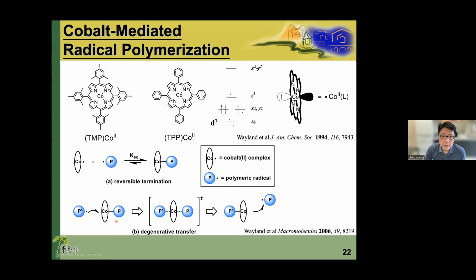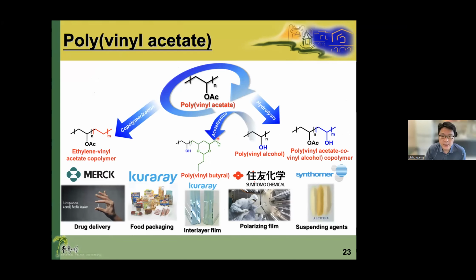And the feature of cobalt-mediated radical polymerization is the remarkable capability to control vinyl acetate. If you remember, I told you that most of the methods can control the acrylate polymerization quite well, but only cobalt can control the vinyl acetate polymerization quite well. Then polyvinyl acetate is a daily used material, and in most situations it is used as adhesive, and it could be hydrolyzed to form the polyvinyl acetate and vinyl alcohol copolymer, or hydrolyzed further to get polyvinyl alcohol.